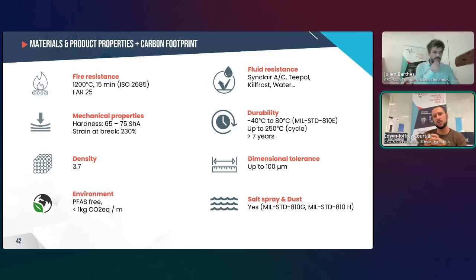And this is also the idea of this kind of enhanced silicone. So there we can produce the silicone with hardness between 65 to 75 Shore A, with high elongation at break, with the same resistance to fluid and durability that we presented before for the EMI gasket, and also a very low environmental impact, and of course PFAS free.